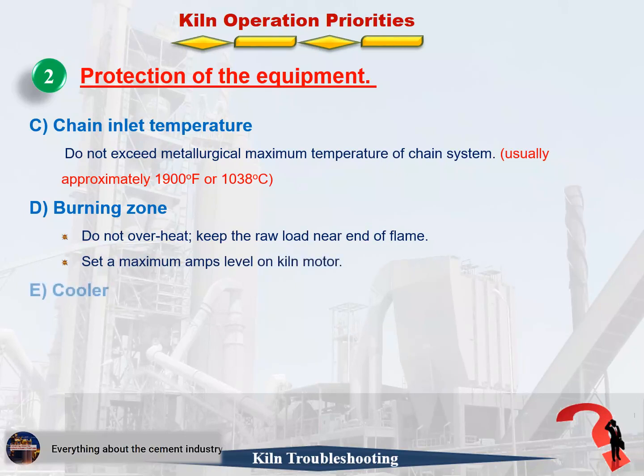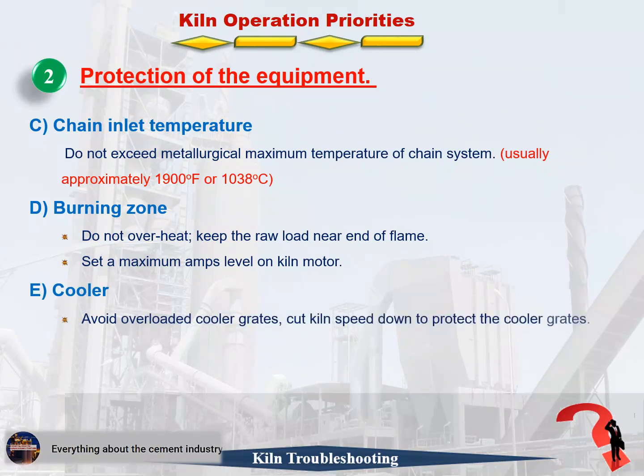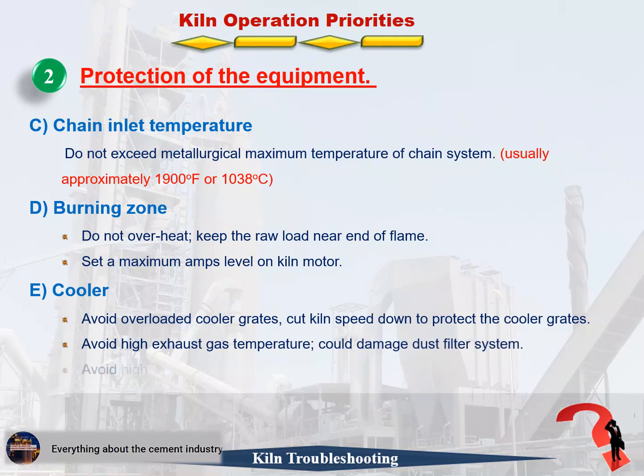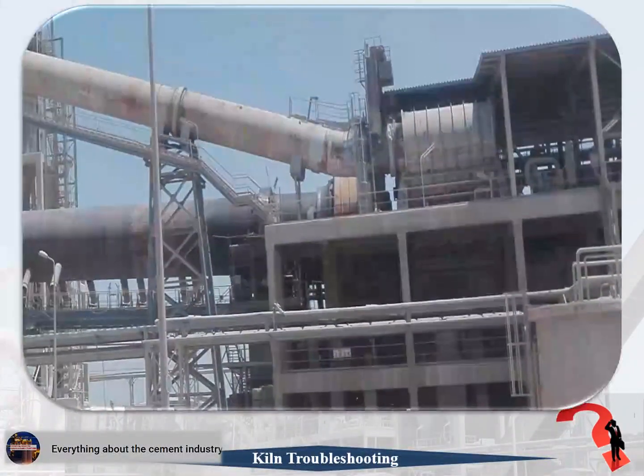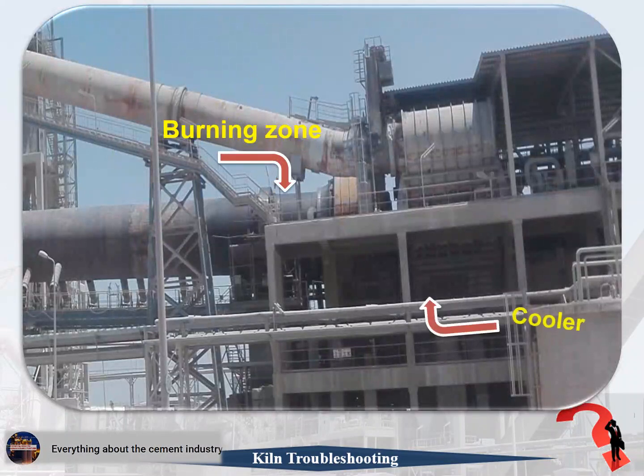E. Cooler. 1. Avoid overloaded cooler grates, cut kiln speed down to protect the cooler grates. 2. Avoid high exhaust gas temperature, which could damage the dust filter system. 3. Avoid high clinker temperature, which could damage the clinker evacuation circuit. This picture shows the burning zone, cooler, and kiln.